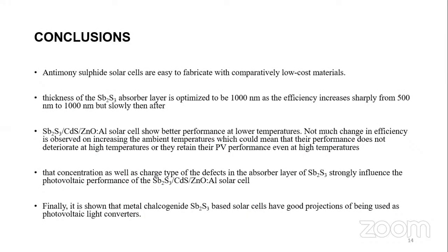So now I would like to conclude that from this study, we have made some conclusions that antimony sulfide solar cells are easy to fabricate, they are low-cost materials, and they can be an alternative to the existing technologies. The thickness of the Sb2S3 absorber layer in this study was optimized to be about 1000 nanometers, as the efficiency increased sharply from 500 to 1000 nanometers, but after that, the rate of increase of efficiency declined.